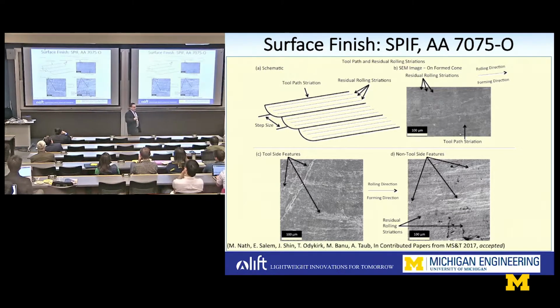And so what we know is the strain path is different in stamping than in incremental forming. That leads to different microstructure evolution. That leads to different properties and different surface finish. And we really need to look at fatigue critical parts, so that's what we're going after next.